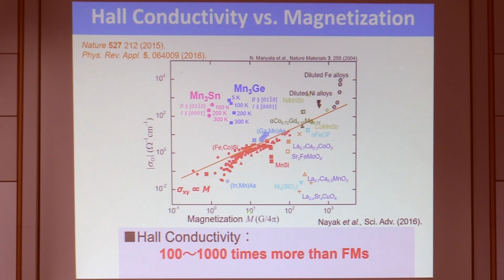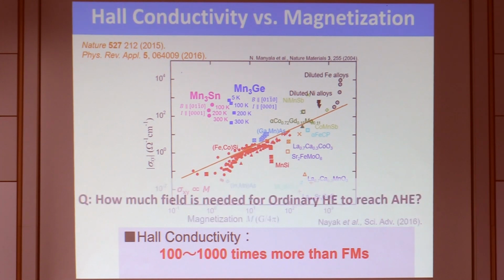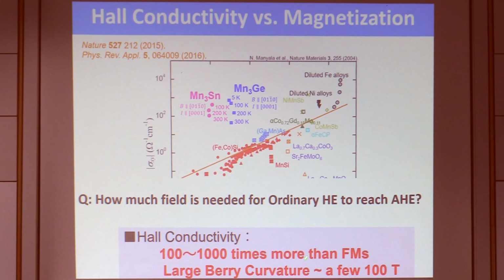And if we ask how large a magnetic field is necessary for the ordinary Hall effect to reach the anomalous Hall effect, using the ordinary Hall coefficient of these materials, it turns out that a few hundred Tesla is necessary. So the amount of Berry curvature in the momentum space is equivalent to the size of these external fields.